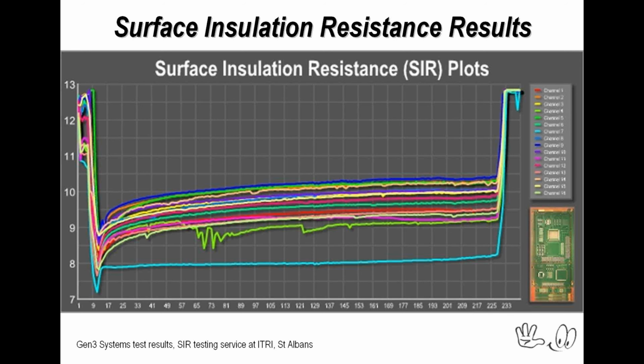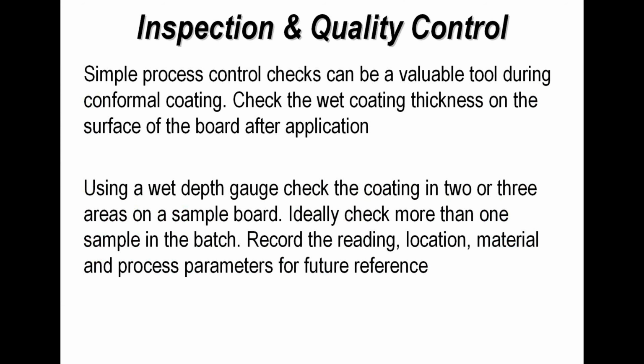The green line, the light green line, where you're seeing a little blip, perhaps is an area which might be questionable on one of the test coupons, and perhaps the rest of the test results you're seeing are satisfactory. Again, you set your criteria based on international standards, but this is a measure of the performance of the whole process, so that all the materials, the coating, etc., under adverse conditions.